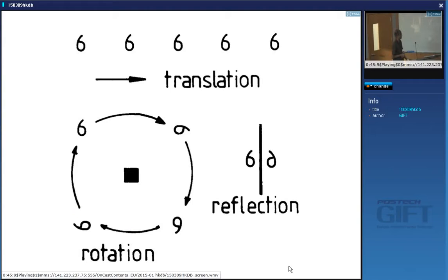We also need to think about symmetry. We've already talked about that by identifying crystallographically equivalent planes and crystallographic equivalent directions. So in the cubic system, we had 6 cell edges, which all have exactly the same properties. If I change that to tetragonal, then the A axes are identical in the basal plane, but the C axis is different. So the symmetry changes, and now I have 4 equivalent 1, 0, 0 directions, not 6, okay? And so on.